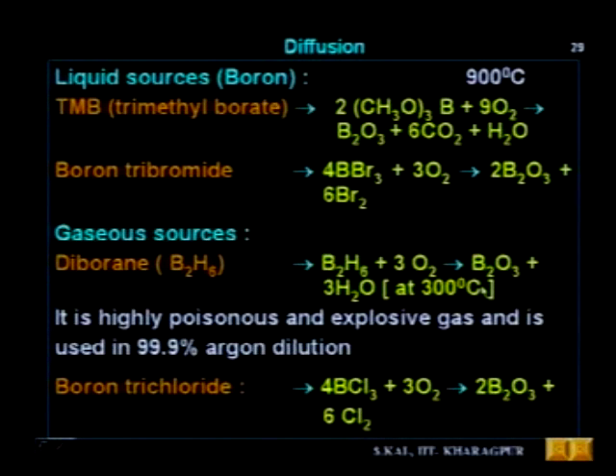at 300 degrees centigrade. And one point I should mention here, that gaseous sources, the hydrides, are highly poisonous in nature, and explosive also. B2H6 is a highly poisonous and explosive gas, and this particular gas is never used in a concentrated form. Before sending into the furnace, it is diluted in argon or sometimes nitrogen, 99.9% argon and only 0.1% or 0.2% is the dopant gas. So a raw hydride gas, either diborane or phosphine, is never used. It is highly poisonous and explosive in nature.